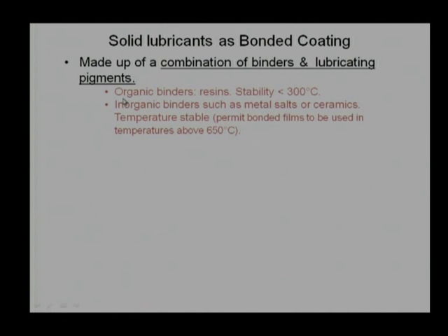That is why this kind of solid lubricant coating should be used when the maximum operating temperature is lower than 300 degrees centigrade. Otherwise, at high temperature, they will start liquefying and flowing, and the solid lubricant will not stick and will not remain effective. But if the operating temperature is lower than 300 degrees centigrade, then we can use resin based binders to stick the solid lubricant to the components where desired.